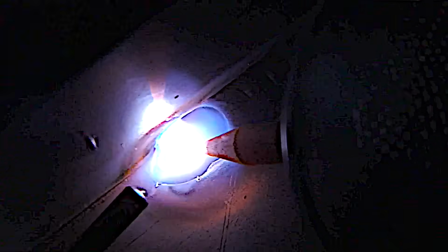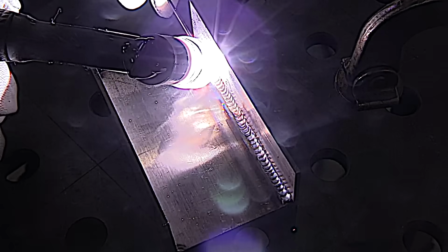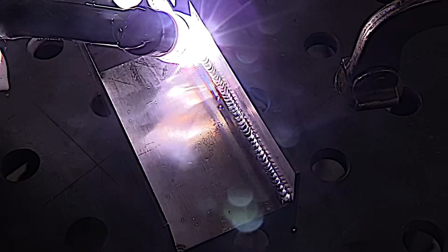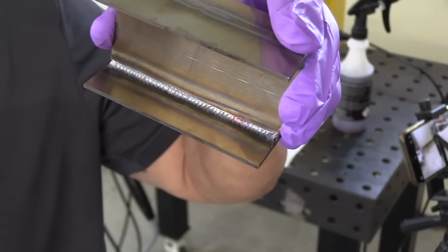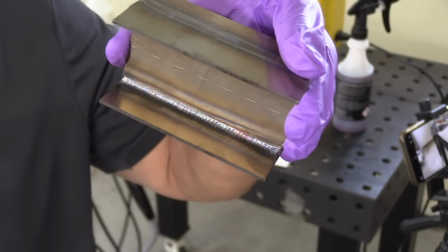I'm trying to take very short steps here in between dabs of filler metal. If you step out too far and wait too long before dabbing filler metal, that's where you melt through. And there are some requirements to not melt through on either test welds or even production parts of this thickness. That oxide layer, as I mentioned before, is not as corrosion resistant as pure stainless steel.